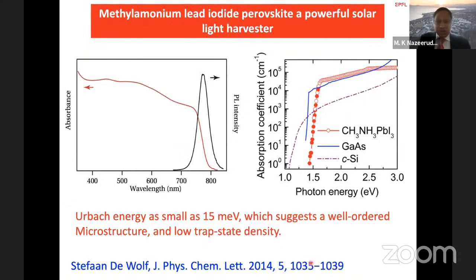Now, as I mentioned in the first point, it absorbs all the visible light as shown here. It absorbs from 400 to 820 nanometers. And wherever you excite, we have a very nice emission maximum coming around 790 nanometers. This material has very nice characteristic features similar to gallium arsenide. The blue line is the gallium arsenide, with a very sharp onset. And similarly, methyl ammonium lead iodide has a very sharp onset. This shows the very low trap state densities in this material.